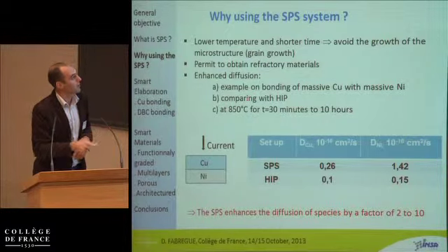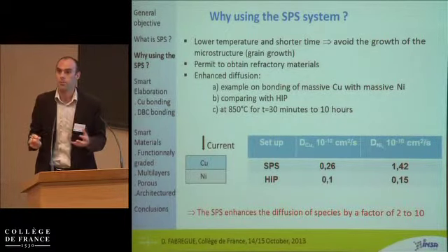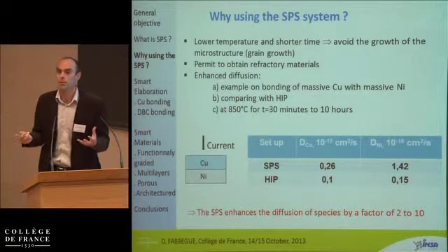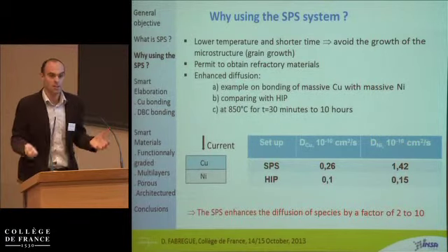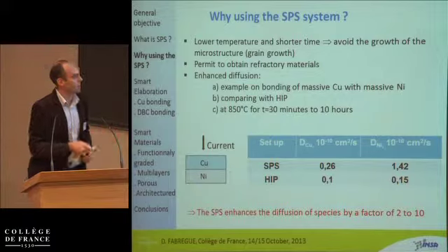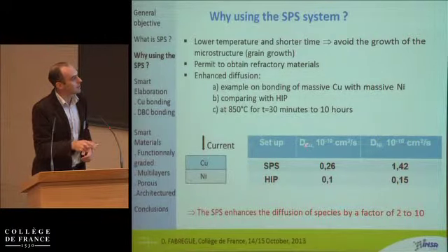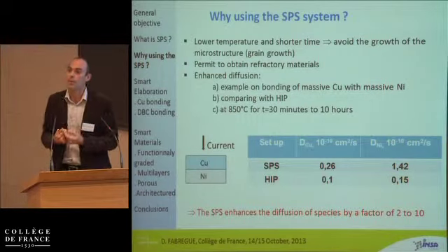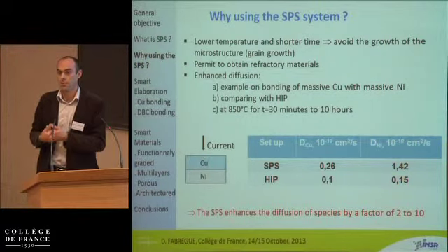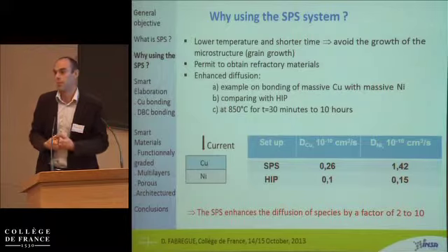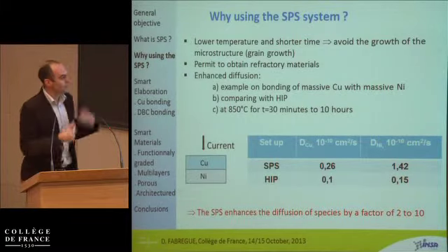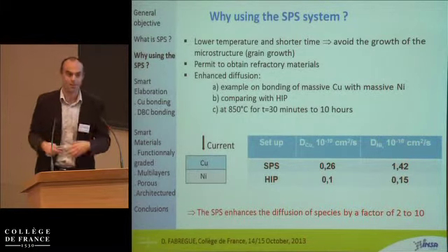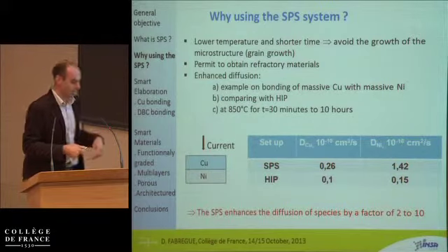We compare that with the HIP, hot isostatic pressing, which is exactly another sintering system, where the heating is just a classical furnace. And this is the diffusion coefficient for copper and for nickel. As you can see, there's a real enhancement of the diffusion of these species in the case of spark plasma sintering. So that explains some of the things like lower temperature and shorter time. So can we use that now?